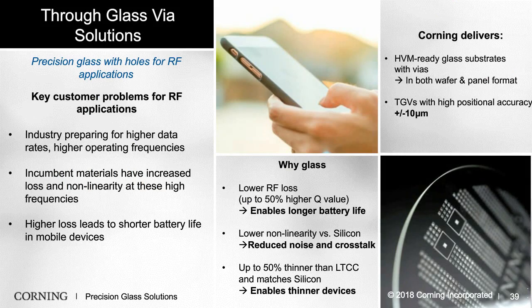So in summation, Corning is investing quite a lot in glass, both from a compositional standpoint as well as producing the through glass vias. We think that there are very attractive markets within the RF world that could be served, where glass has both performance and packaging and size and overall cost benefits. We think the lower losses can certainly be used in consumer applications where battery life is key. We think that we can impact at the component level as well as at the module and at the system level. And our process approaches are creating very high accuracy elements and giving an order of flexibility with regard to the composition itself, as well as thickness and height choices for the system designers.